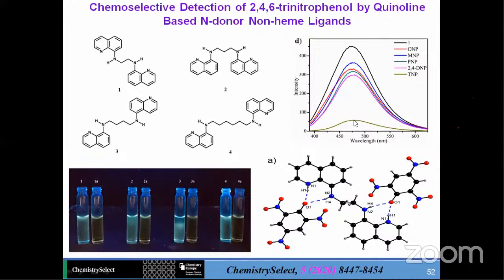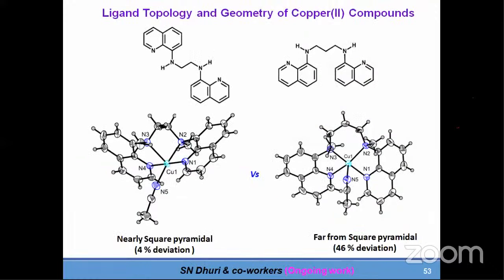Finally, interestingly, for this brownish, yellowish solution we crystallized it and got a crystal structure. Most of the time, reports say that a resonance energy transfer mechanism is taking place, but in this case we ruled that out. In fact, the quenching takes place at the ground state, because the adduct forms directly, and the adduct was characterized by a single crystal study.